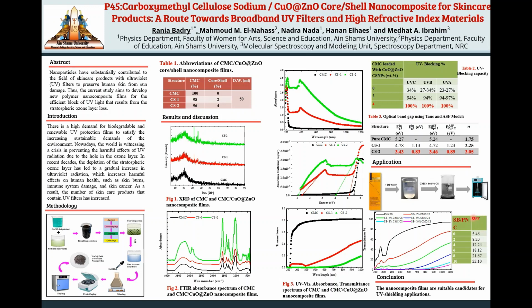Additionally, we calculated the sun protection factor for pure sunblock, which was found to be 5, and we found that it increases to 22.1 with the addition of 10 weight percentage of our polymer nanocomposite, which is a very good result. According to the published report by the World Health Organization, they recommended using sunblock with a sun protection factor between 15 and 50, which is the best for use. Our conclusion is that the nanocomposite filters are suitable candidates for UV shielding applications.